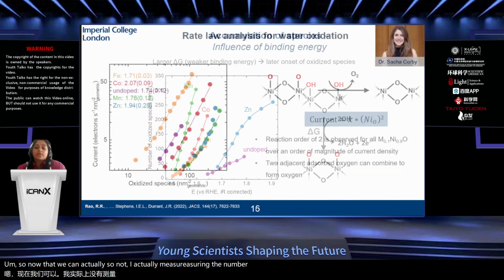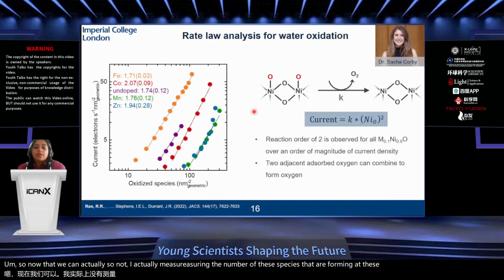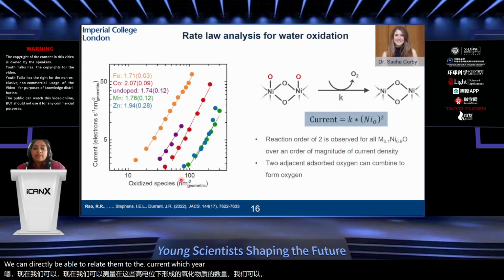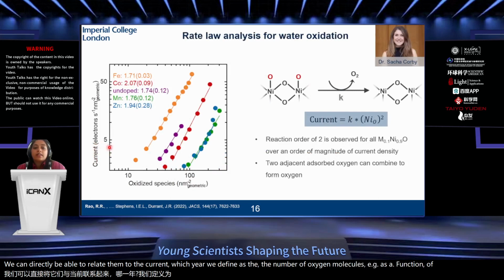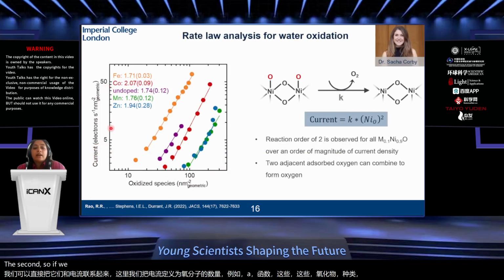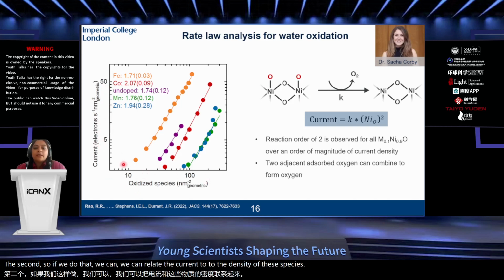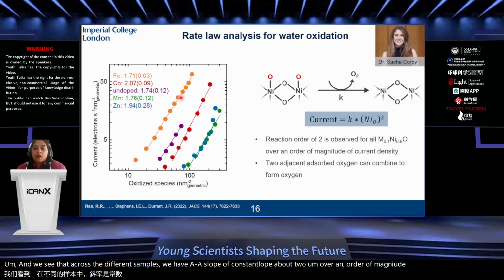So now that we're actually measuring the number of these oxidized species that are forming at these high potentials, we can directly relate them to the current, which here we define as the number of oxygen molecules, for example, as a function of these oxidized species per second. So if we do that, we can relate the current to the density of these species. Here I've plotted a log plot of the current versus these species, and we see that across the different samples, we have a constant slope of about 2 over an order of magnitude of increasing current density.